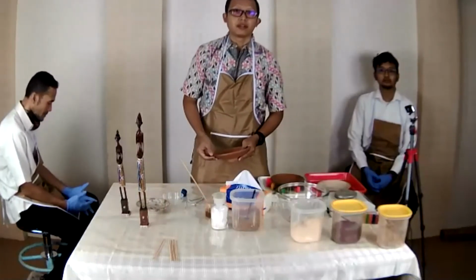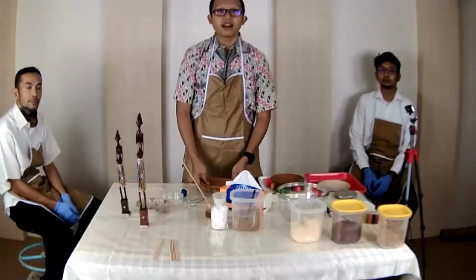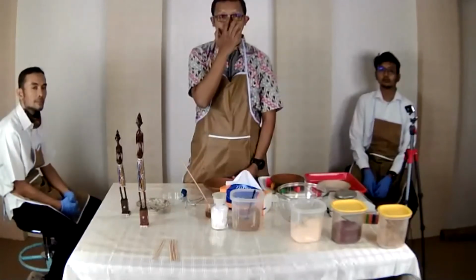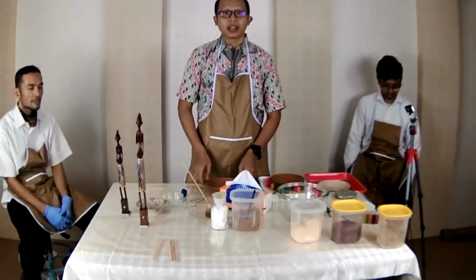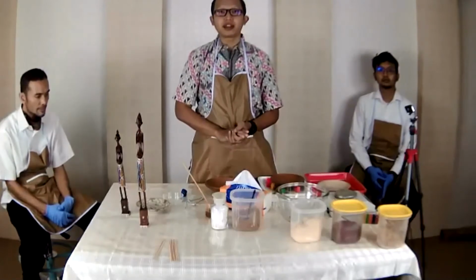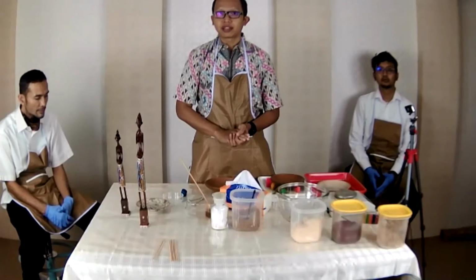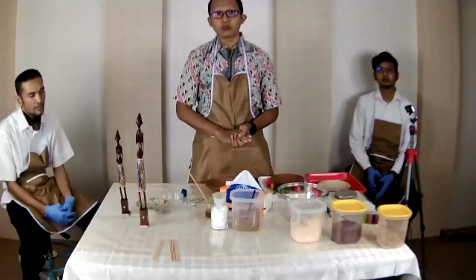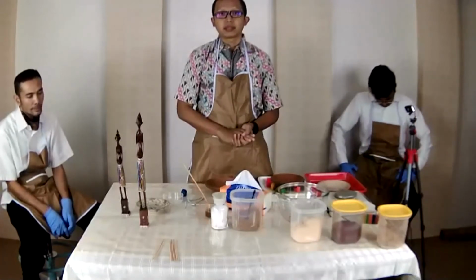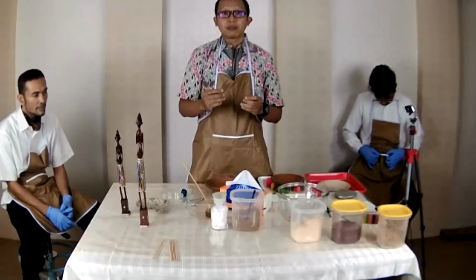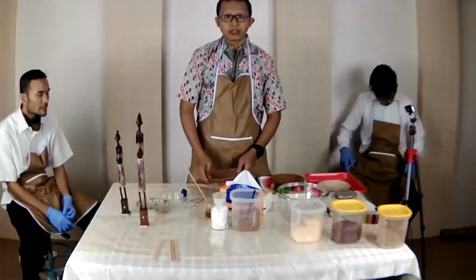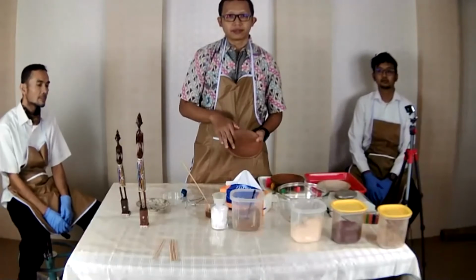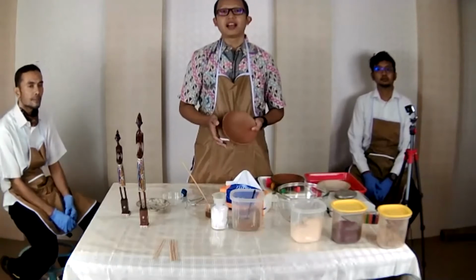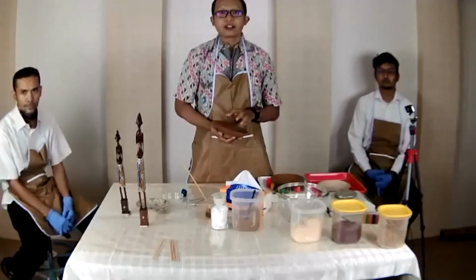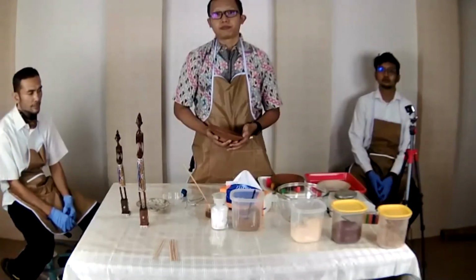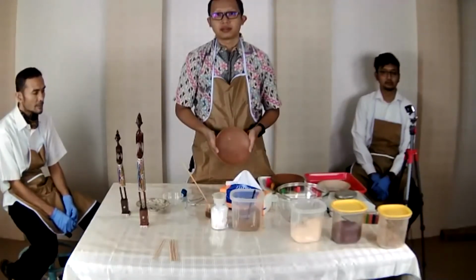There's also a possibility of an external factor, like the humidity of the room where you store the repaired ceramic. If the room has high humidity, about 90% humidity in a continuous condition for a very long time, it might be able to disrupt or dissolve the joint fragments. We make sure that the procedure is correct, and then we make sure that the room where we store it is not too humid.